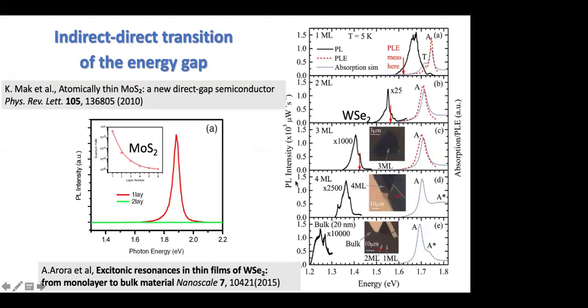As a result, this is quite a famous picture showing the difference between luminescence from one monolayer or two monolayers of molybdenum disulfide. The intensity of the excitonic resonance really changes incredibly when you go from a few layers to just one monolayer.